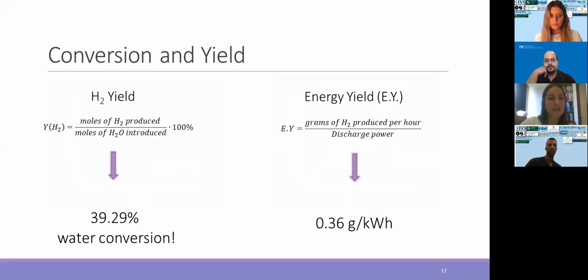From the left here, you can see the H2 yield, which tells you how much water converted into hydrogen. We got almost 40%, which is pretty amazing considering the fact that we didn't even know that we produce hydrogen. On the right-hand side, you can see the energy yield that tells you how efficient your system is. We got 0.36 grams per kilowatt hour, which is a reasonable energy yield. Not that great, but these are very preliminary results, and we think that we can even produce more hydrogen.